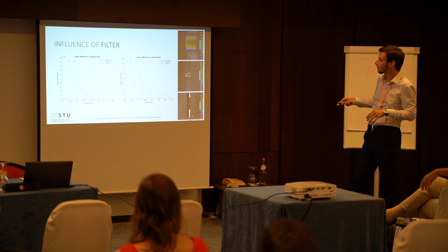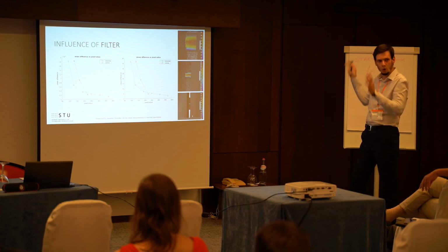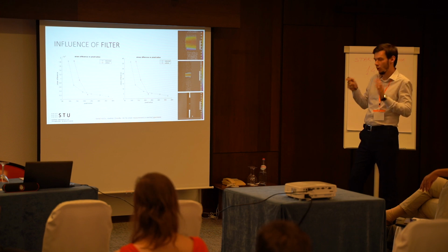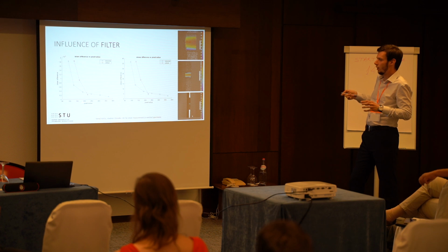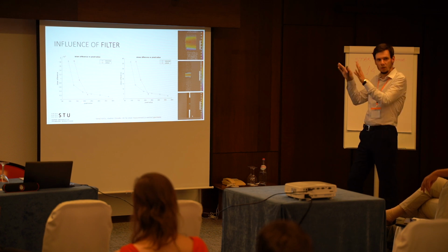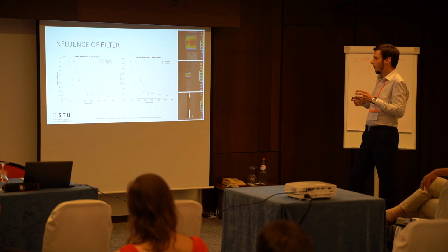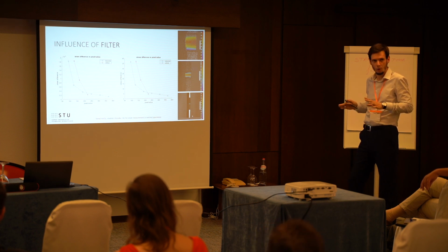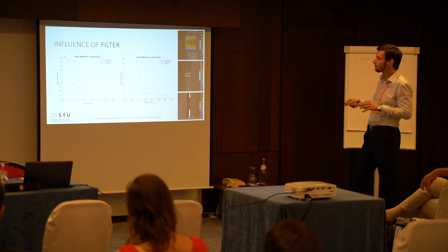This chart is the same, just recalculated in a linear elastic region to the stresses for steel as a material. With these data and all the measured data, we considered that all the notches that were larger than 200 pixels per radius were relatively well measurable, or for us relatively well measurable.